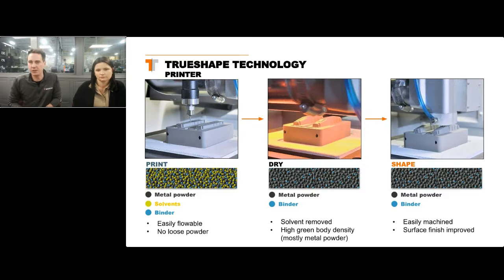What's super critical now is that after every single layer, we are going to dry this paste material. This is going to remove the solvent and actually firm up the layer a little bit. So here we're moving from a toothpaste-like material into more of a dense foam. What's actually happening here is that we're taking the part and turning it into a very high green body density. If you're familiar with powdered metal, you'll know why that's so important, and that's to minimize the shrinkage right here. We're actually packing this powder very, very densely so that when it goes into the furnace, it doesn't have to shrink as much.